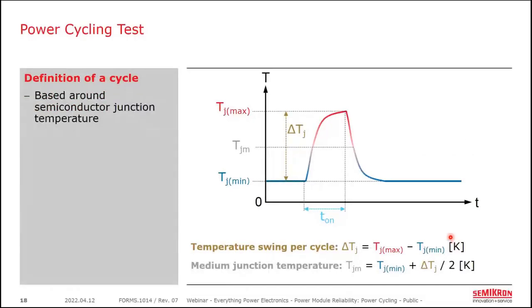And so, what I'm showing here is a single cycle where the device is heated for a certain on time, a heating time, a T on. And the junction temperature is going from a minimum to a maximum and back to the same starting minimum value. Our delta T that we define is simply TJ max minus TJ min. And there is also something called the medium junction temperature, TJM, that's defined as the midpoint between the minimum and maximum. So we have three parameters here: T on, delta TJ, and TJ medium that define a single temperature cycle.